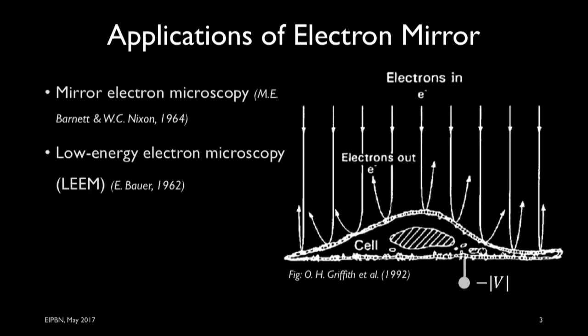There are two advantages of these techniques. One is that if the sample is very sensitive to energetic beams of electrons, in this case we're only very gently interacting with them. The other advantage is that they're very surface sensitive, because we're not interacting with the bulk of these samples. In the case of mirror electron microscopy, we're not even interacting with the actual sample, only above it, so we can only see a kind of contour of the sample. And in the case of LEEM, we can only see the very outermost surface of the samples.